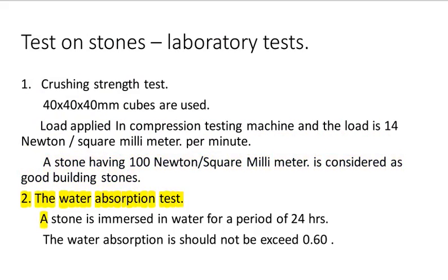2. The water absorption test. A stone is immersed in water for a period of 24 hours. The water absorption should not exceed 0.60.